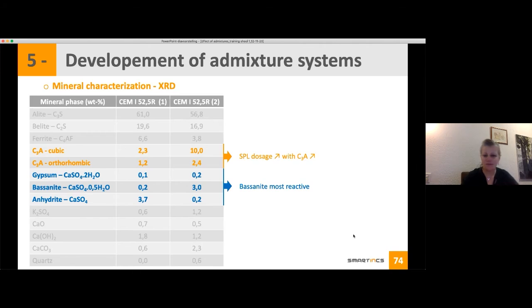And to make things even more complex, we don't have only one form of sulfate in cement, we have 3 forms of sulfate. You can have gypsum, bassanite, or anhydrite. But they won't have the same dissolution rate. When in contact with water, some will go into solution really fast and react really fast, and some will dissolve very slowly, releasing the sulfate ions slowly, so they can react with your C3A in a more controlled way.